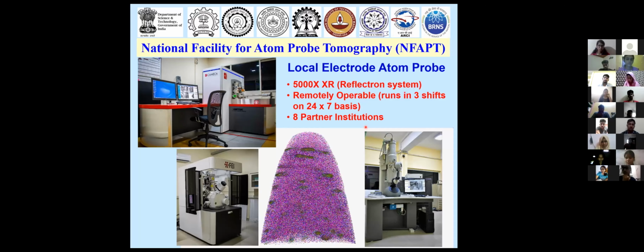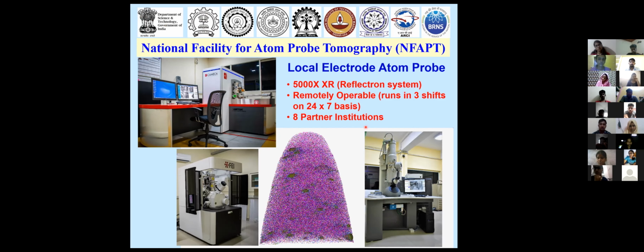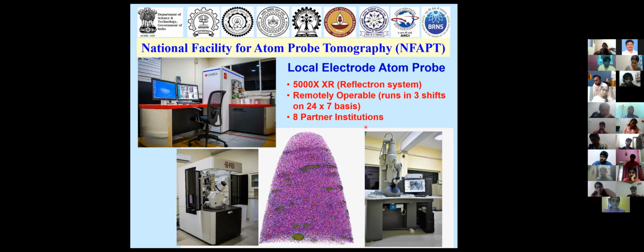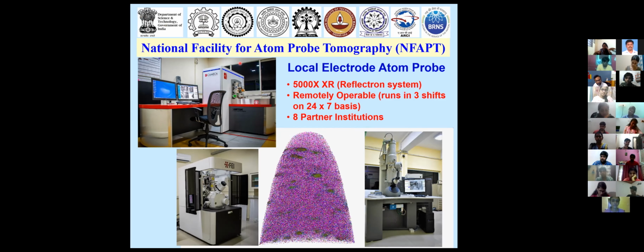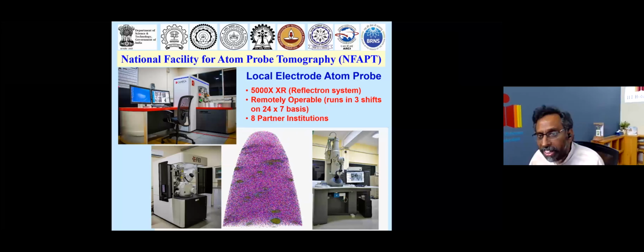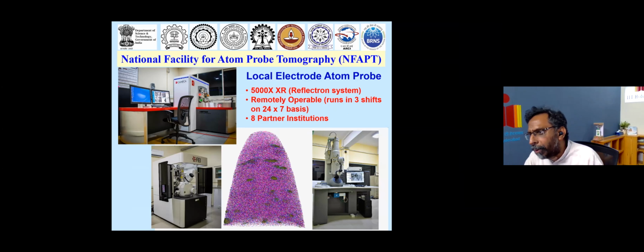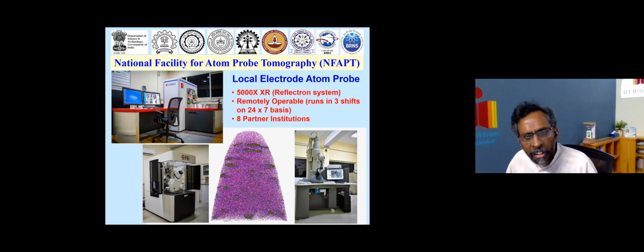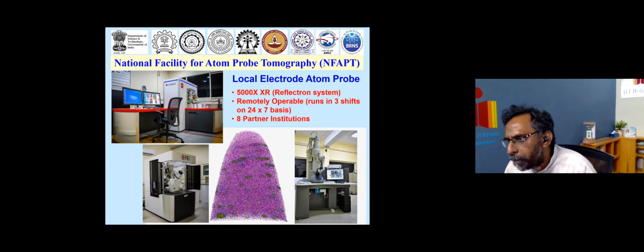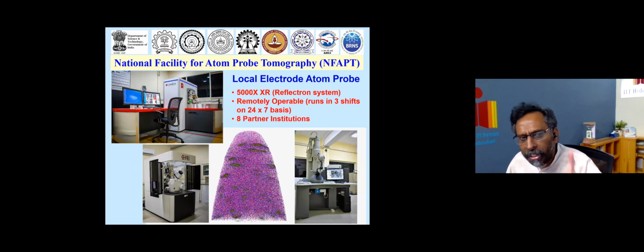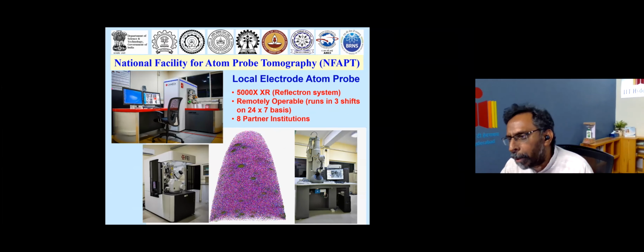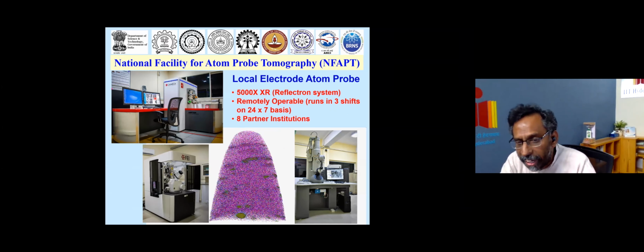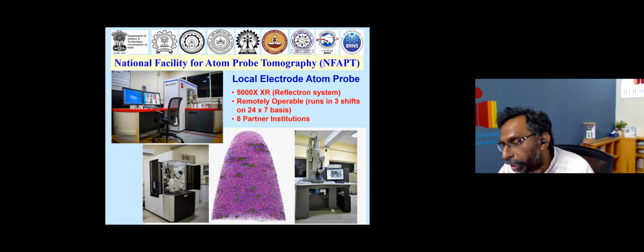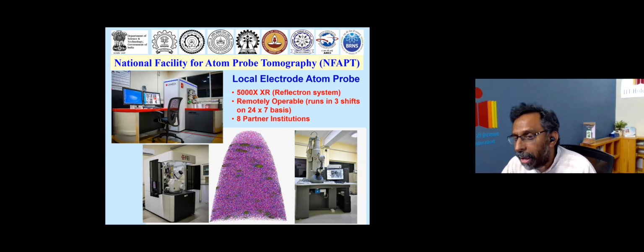In the whole world, this is the first remotely operable atom probe tomography technique, where you can send a sample to us, we polish the sample and put it into this atom probe. What you see on the top left is what is called an atom probe. It is called LEAP, local electrode atom probe. You put the sample inside, and then somebody sitting in IIT Bombay can operate this. You just need a workstation, what you see on the table here, with the software loaded. IIT Bombay sends a sample to us, we put the sample inside, and the IIT Bombay person sitting in front of the computer can operate this particular microscope and collect all the data. This is the beauty of this thing. First time we have been able to do it, and we run it in 3 shifts.